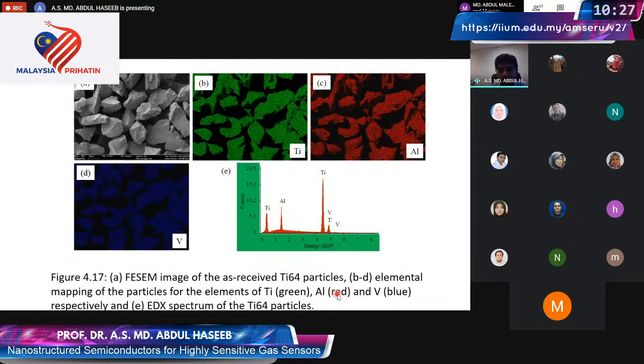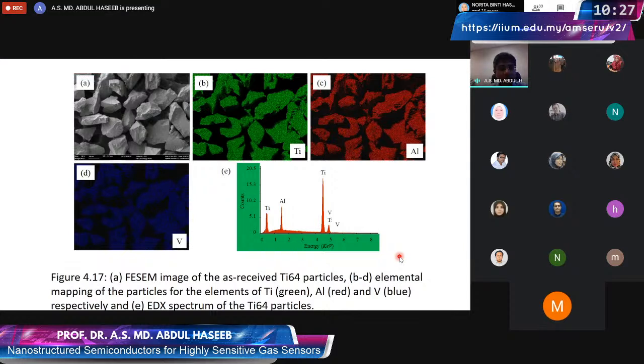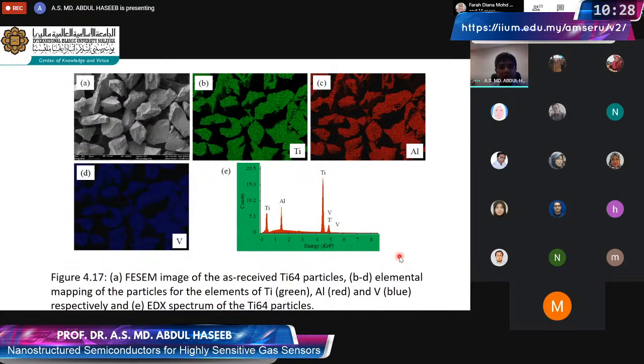And maybe I have to give some brief introduction to this particular type of particle, which is called Ti64. It's a commercial alloy of titanium, which is very easily available. It contains 6% aluminum and 4% vanadium. And the reason why we started this with this alloy is that we could also produce oxide on pure titanium. But looking at the literature and based on our own experience, we found that producing good nanowire on pure titanium by this oxidation method is difficult, and the window of the parameters that we need to achieve is very narrow. Then we thought that this alloy, which is very widely available, let us try this.